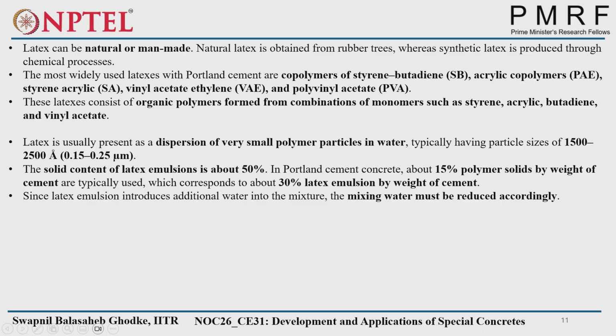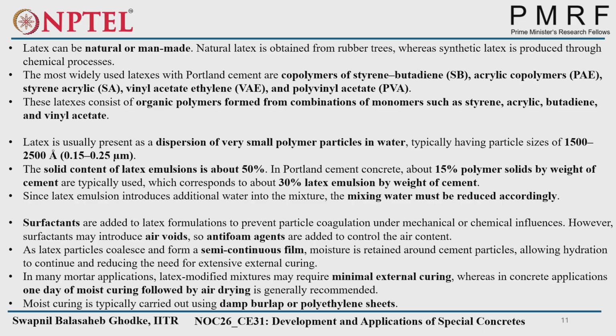Since latex emulsion introduces additional water into the mixture, the mixing water must be reduced accordingly. Which additional water are we getting? Latex, as we already saw, is a combination of 50% water and 50% small dispersed polymers. That additional water is provided with the latex, so the water we add into the concrete can be reduced to whatever is required for the hydration process.